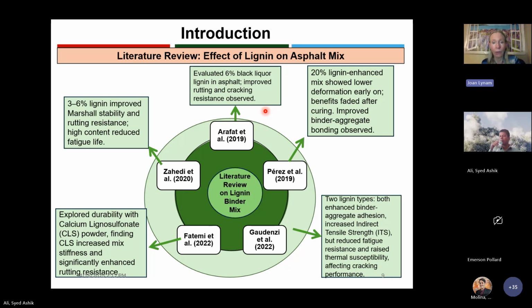You can see Perez et al. in 2019, 20% lignin they put in their asphalt binder, and it was pretty good for a while, but then the benefits tended to go away after time, although they did get improved binder aggregate bonding. So that was one thing. If you look at the Gaudenzi study on the bottom right, it was mostly wood that they used, and they did find increased indirect tensile strength, but they kind of had problems with when they went to different temperatures because it affected the cracking performance.